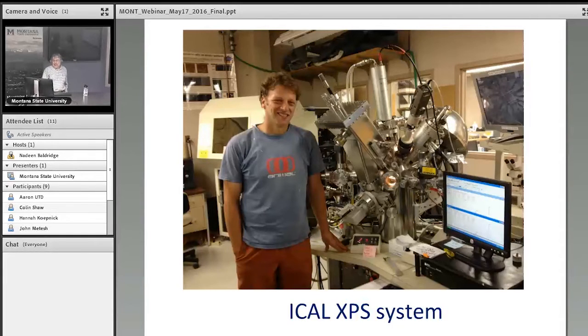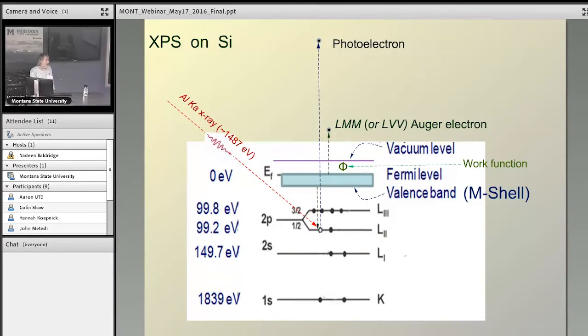So let me just review a couple of fundamentals. Some of you are bored, but some of you may not even know what X-ray photoelectron spectroscopy means. You send in X-rays of fixed energy, in this case aluminum K-alpha, monochromatized, 1,487 eV. It gives all of its energy to this atomic structure here, it's a silicon, actually, an electron in one of the shells. So it takes it up to this level here. The length of this arrow is the same as this arrow. This is called the photoelectron. It goes out. These are the sharp peaks.